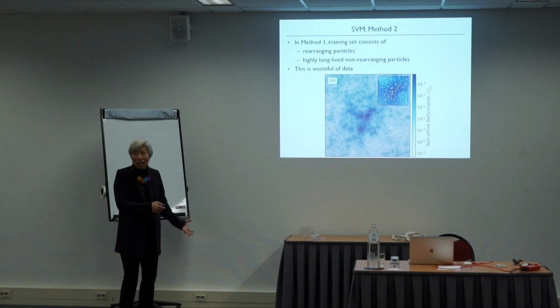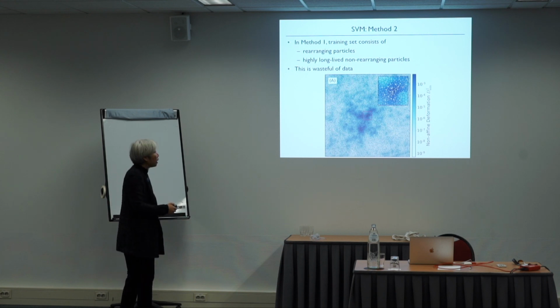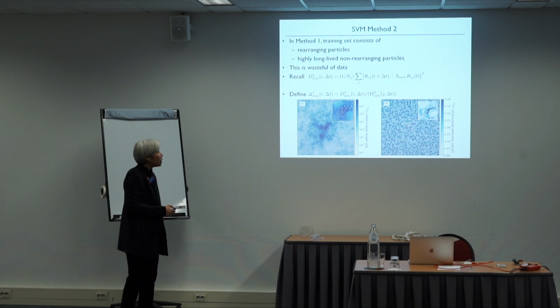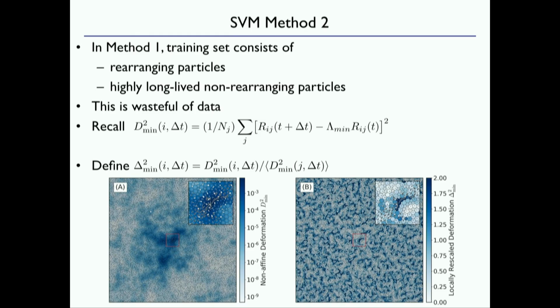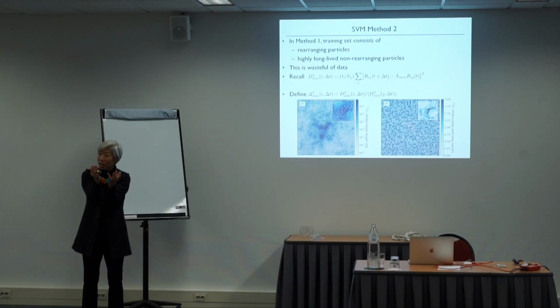So what we do instead is to recognize that there are lots of places here that could have rearranged that didn't. They maybe had the same structure as this particle here, but they didn't happen to rearrange. Can we pick those out as well? You can pick them out by looking at fluctuations of this D squared min. In other words, if I look at D squared min compared to some neighbors, then ones that are locally larger are more likely to rearrange. So even though there's this background power law decay, some of these might have moved further than their neighbors, whereas others might not have.